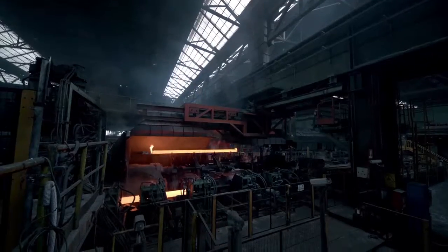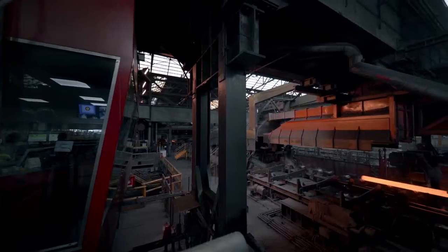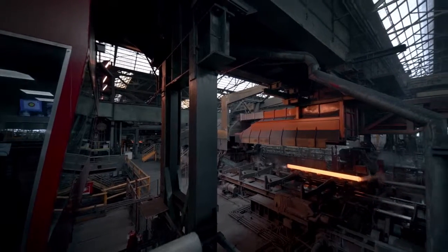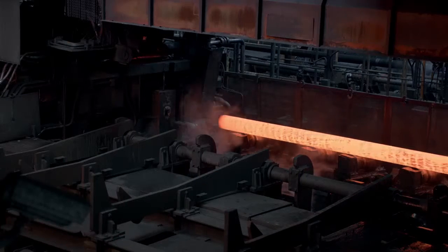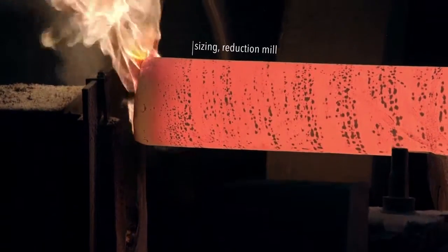elongating the shell and transforming it into a mother pipe. The mother pipe is then sent to the last stage of the rolling line, the sizing mill, to set the diameter and wall thickness of the tube according to customer needs. The mother pipe is sized, reducing the outside diameter between 3 to 7 sets of double rollers.